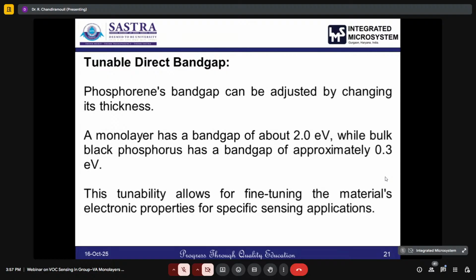And the band gap can be fine-tuned. The important feature of using phosphorene is that the band gap can be adjusted by changing its thickness, whether we use bulk phosphorus, a few layers, or a monolayer. Depending on that, we can tailor the band gap. A monolayer may have a band gap of 2 electron volt, whereas bulk black phosphorus has a band gap of only approximately 0.3 electron volt.